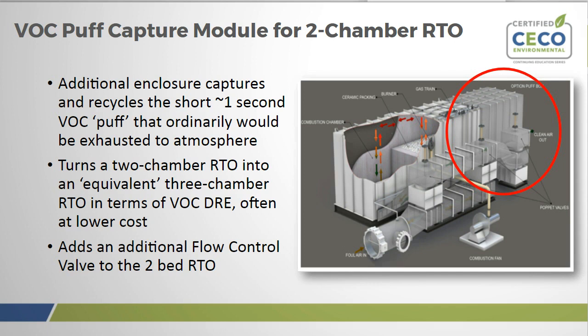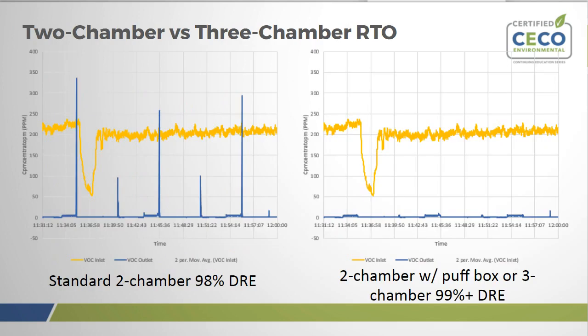So here we have an example. Hopefully this kind of helps for those who like seeing graphs. So we have the difference between a standard 2-chamber on the left, and a 3-chamber, or you could say a 2-chamber with a puff box on the right. So the yellow line indicates VOC inlet concentration, and the blue line indicates the outlet. So for the most part, you could think of destruction efficiency as 1 minus the area under the blue curve divided by the area under the yellow curve. Those spikes you see in the blue are the VOC puffs. So every 4 minutes, give or take, depending on how you set it up, you have a VOC spike.